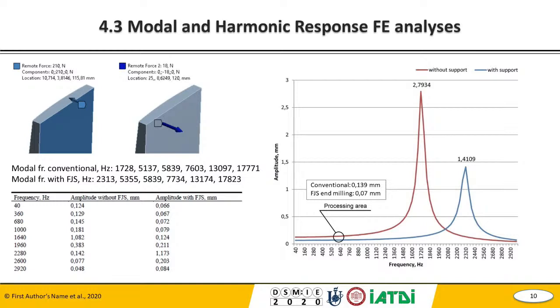So we applied the force to the wall from the side of the milling in both cases, for machining with support and without it, and analyzed a case when we apply machining plus additional support to the whole back side of the wall. And we noticed from the values that there is a shift in natural frequency. You can see it on the slide.